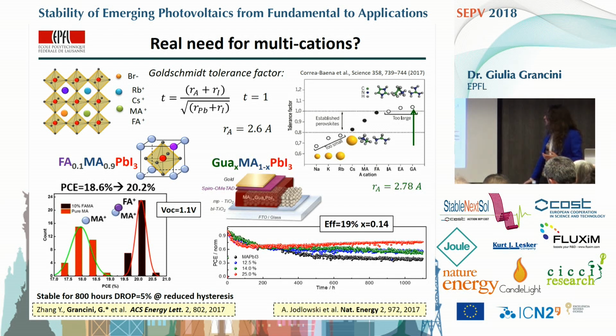And very recently, we have also worked with guanidinium solar cells. Guanidinium per se is too large to form a three-dimensional perovskite. Indeed, it forms a two-dimensional perovskite, but if used in a very small amount, less than around 10%, it can infiltrate into the three-dimensional structure, preserving the integrity of the three-dimensional perovskite. And with this, you can see that, again, efficiency is around 19–20% with good stability. This was done in collaboration with the Cordoba University.